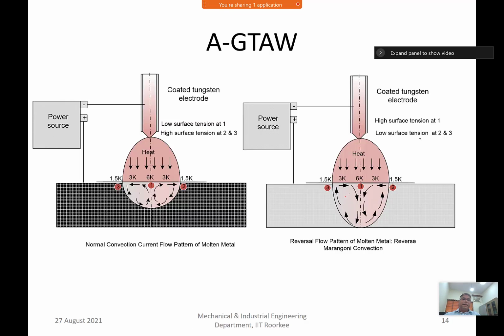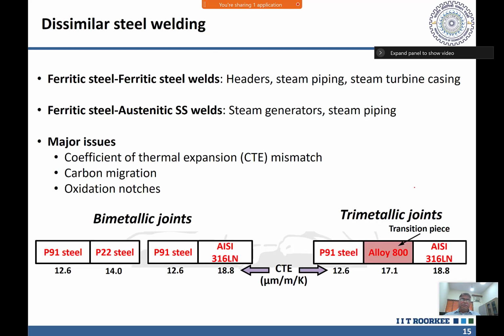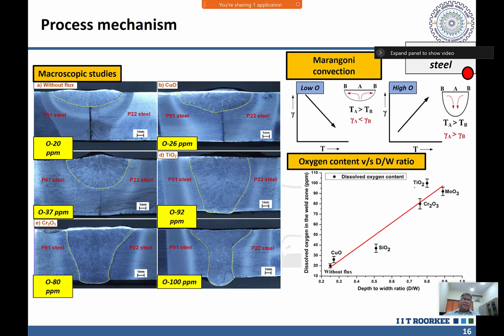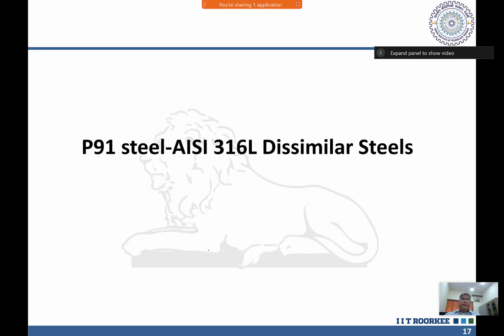So let's take one typical newer development in the GTAW process, where fluxes are used. The fluxes were used, and that resulted in very deep penetration, a high depth to width ratio weld as compared to normal GTAW. Normal GTAW offers 2 to 3 mm penetration, while A-TIG offers penetration up to, we have even welded up to 15 mm using GTAW. And this is the mechanism of how it works. When we use different fluxes, it increases the oxygen content in the weld from 20 to say 100, and that in turn leads to increased depth of penetration for the identical width.